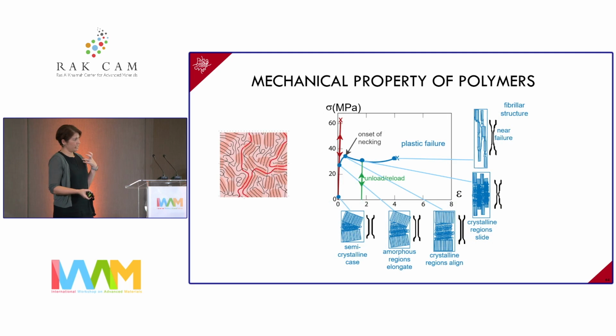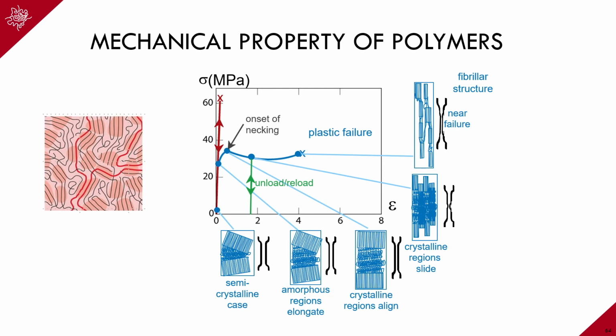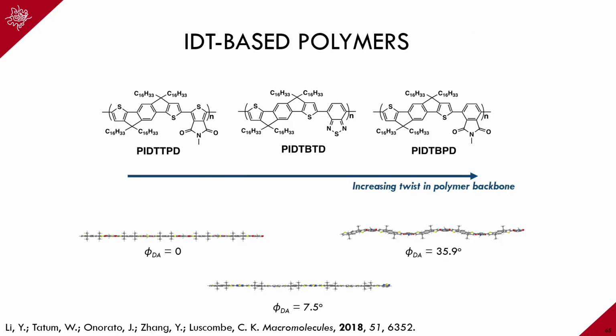And again, being so used to cartoon images and being stuck in the mold of thinking about this particular image, we were like, okay, the reason that it's doing that must be because this model is holding true. Like when you pull the material, you must be stretching out the amorphous chains, and that must be why we're seeing these mechanical properties. And we convinced ourselves that that must be true based on DFT modeling as well. So that squishy polymer, when we did DFT modeling, was showing a lot of torsion, a lot of twist. And so we were like, okay, this twist must be making it more amorphous and making the chains more coiled. And that must be why we're seeing the properties that we're seeing.